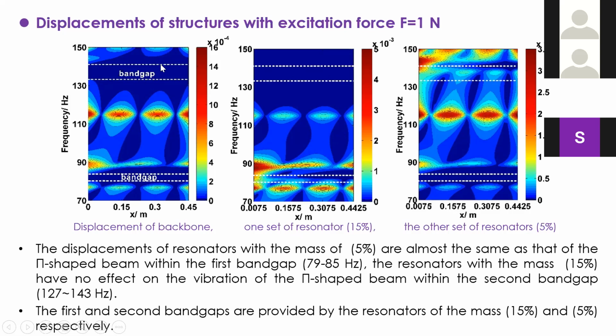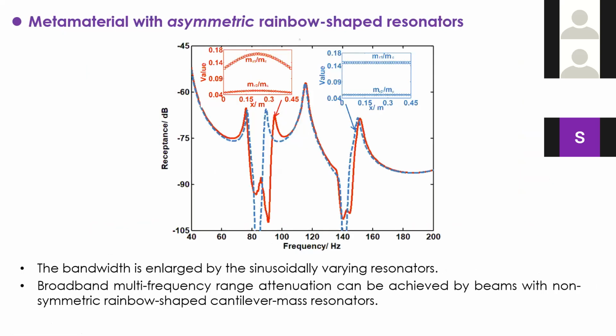If we look at the second band gap, within this band gap the set of resonators with 15% mass doesn't vibrate, but the other set of resonators vibrates very largely within this frequency range, which means the second band gap is caused by the other set of resonators. That's why we can achieve multiple band gaps with non-symmetric resonators. And we can also check this comparison between the material beam with non-periodic asymmetric resonators and the material beam with periodic but asymmetric resonators. We can see the resonator mass distributions like this.